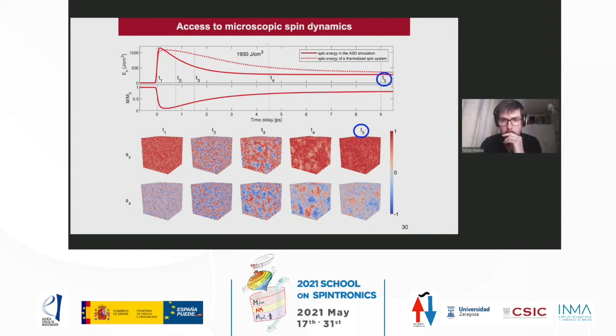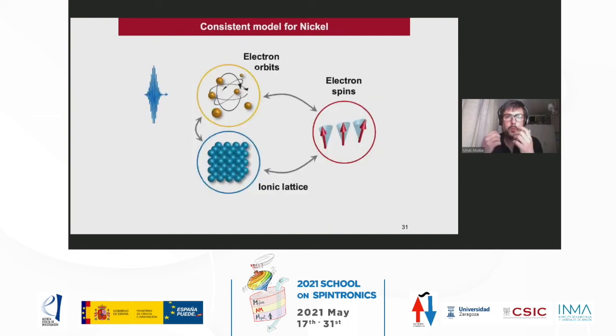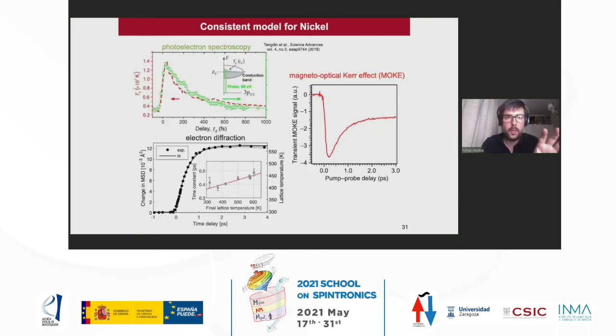So our model, using atomistic spin dynamics, can have access to microscopic spin dynamics, and this model is very common within this community. I presented this consistent model for nickel, which contains all the ingredients usually used in the field of femtosecond magnetism: the electron, spin, and lattice, and they can be measured with different techniques.